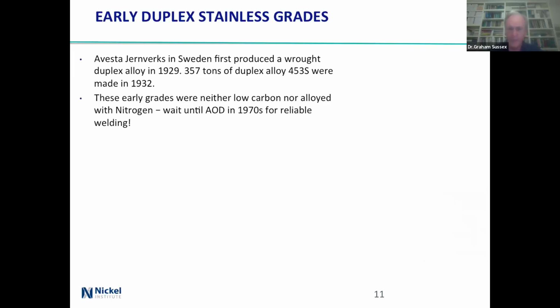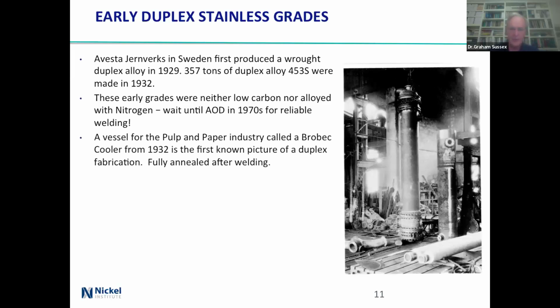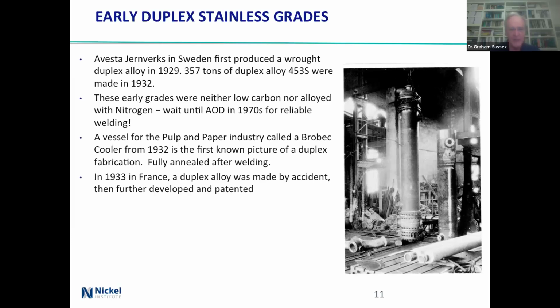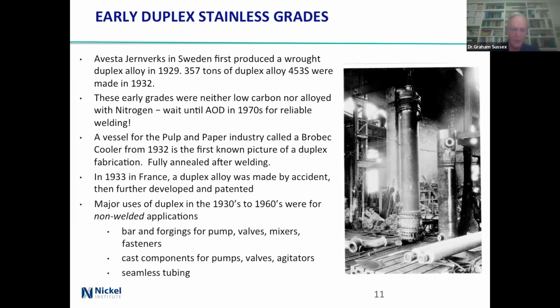So I did the wrong thing. This was a vessel called a Brobec cooler, 1932, fully annealed after welding. Interesting job, fully annealing that. In France, there was a duplex alloy made by accident in 1933, and from about the 30s to the 60s, it was for non-welded applications, bars and forgings, cast components, seamless tubing, basically because you couldn't weld the stuff. There was no good control of the nitrogen in particular, and it was also a bit difficult controlling the carbon.